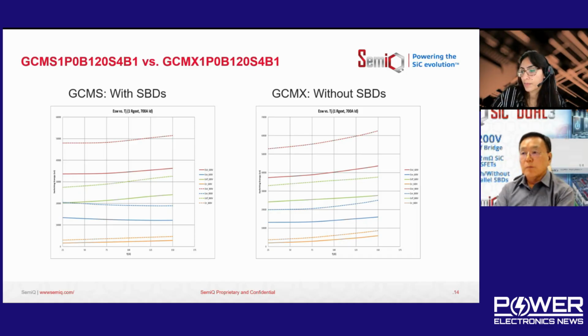And so we try to maximize the power conversion efficiency for those kinds of applications: the highest conversion efficiency and the lowest heat dissipation requirement. By adding the silicon carbide parallel diode inside the module, you can see the overall switching loss is reduced, mainly because of reverse recovery charge reduction. And also the Schottky barrier diode has only constant, fixed junction capacitance.